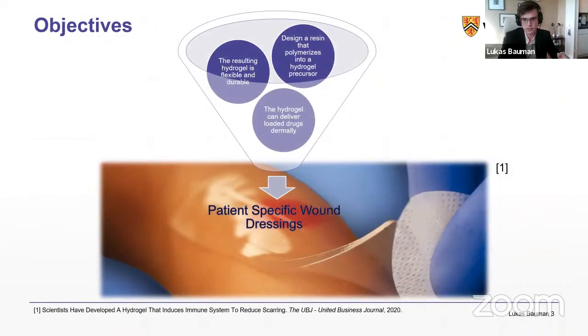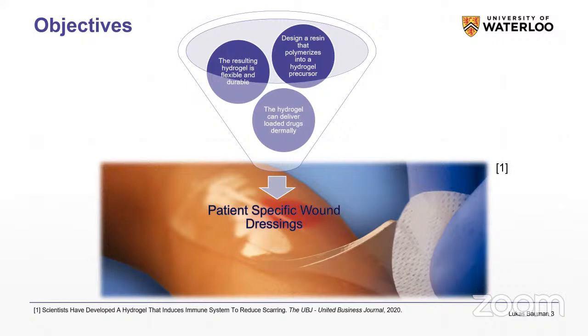So we wanted to design a resin that polymerizes into a hydrogel precursor, and then by swelling it in a calcium salt solution, with the sodium alginate converting to calcium alginate, you create a flexible, durable hydrogel, and then we could load it with hydrophilic drugs to be delivered dermally.